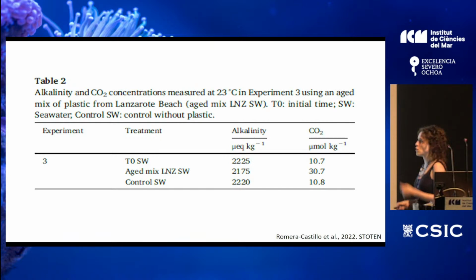And we knew that if the decrease of pH is due to the production of CO2, the alkalinity shouldn't change. But we saw a decrease of the alkalinity in the aged plastic treatment. That means that the plastic is not only producing CO2, which is also seen here, but it's also releasing organic acids that are contributing to the decrease of pH.